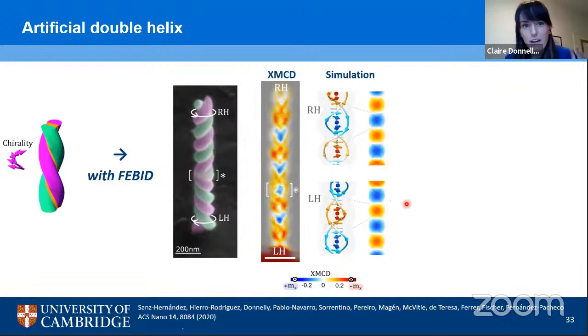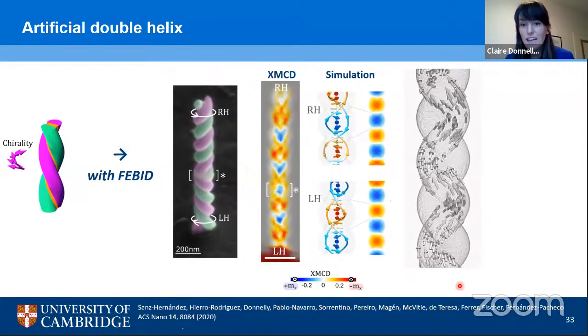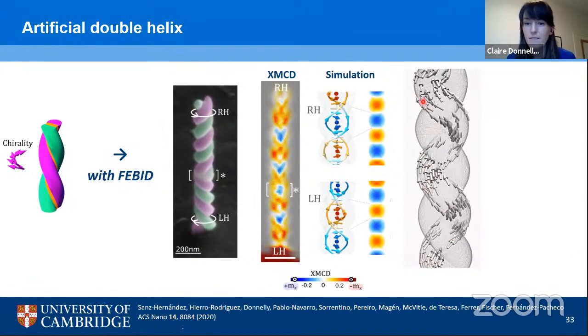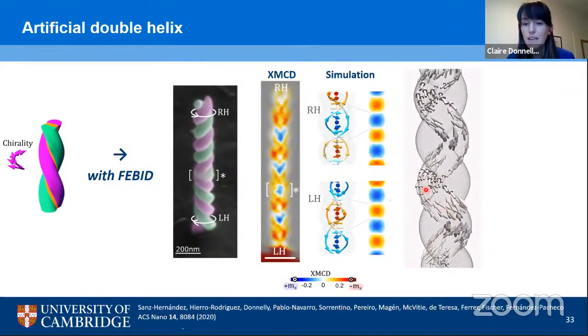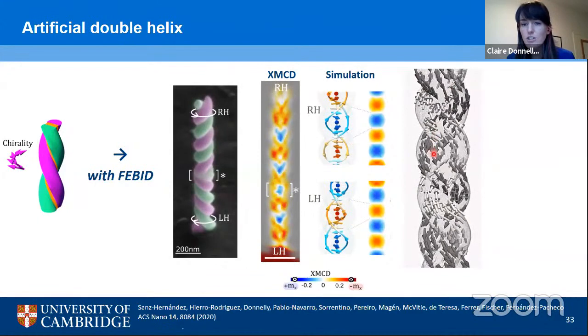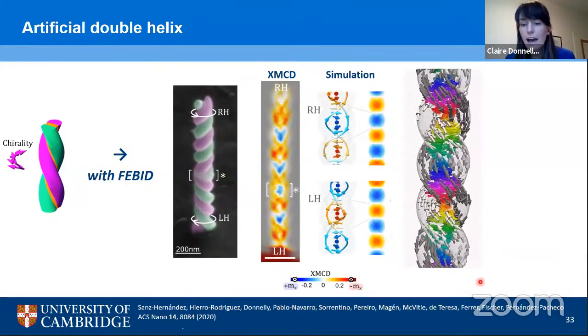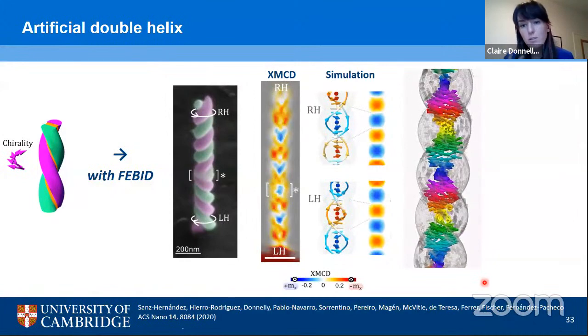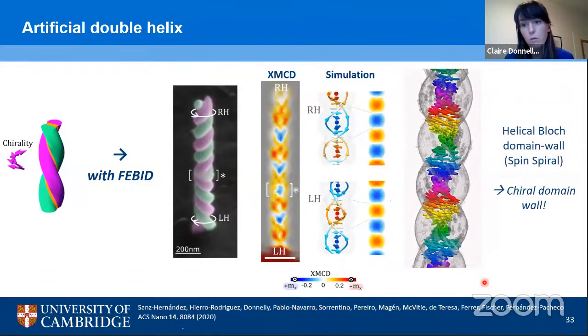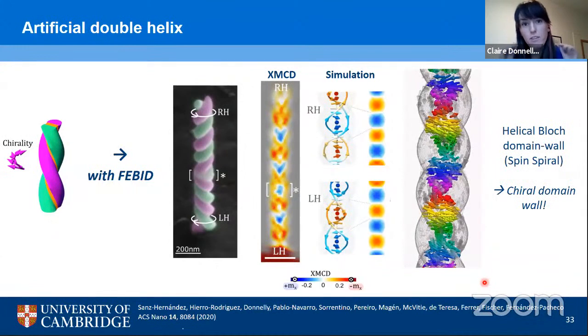Now, it's not just the anti-parallel alignment of these structures which is particularly interesting, but we also need to consider the fact that these double helices are actually overlapping in the middle. With simulations, what we realize is that in between this up helix, shown in white, and the opposite direction of helix, which is shown in black, we have a magnetic domain wall, which turns out to be a helical Bloch domain wall. So we are able, through the patterning of a chiral geometry, to induce a chiral spin texture in the center.